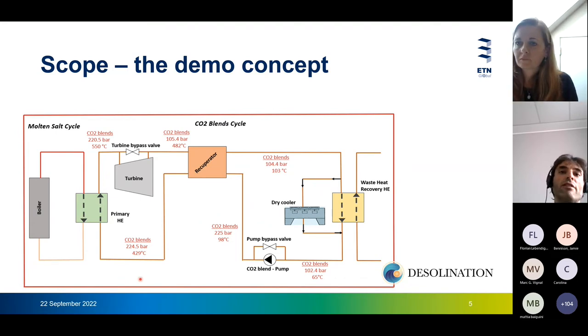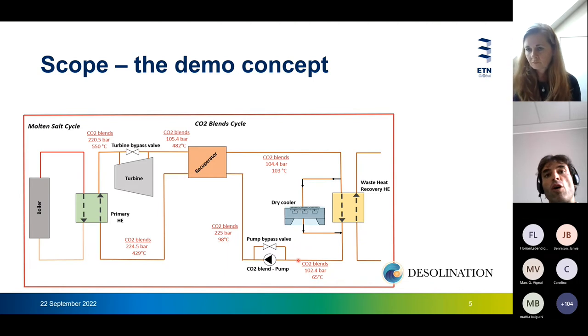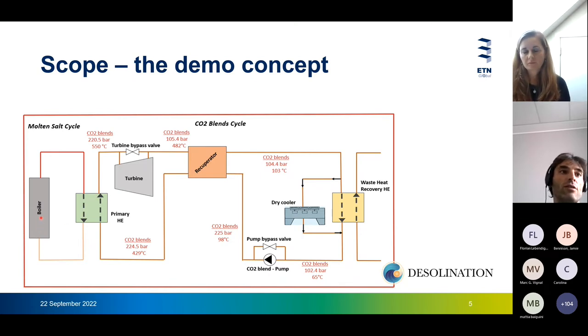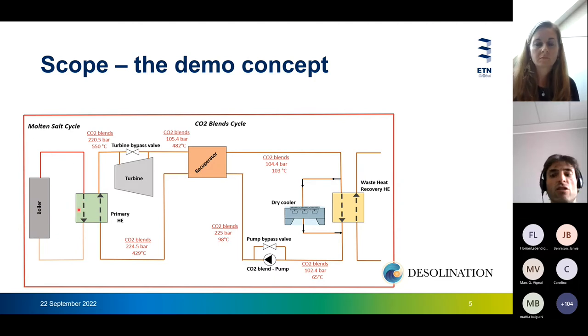This is what is going to be built in the upcoming years within the DESOLINATION project. It is a simple recuperative cycle where you have the pump, because the idea is that the CO2, thanks to the adoption of the blend, is in liquid phase at the inlet. It's compressed, it goes through a recuperator, a primary heat exchanger. We have a boiler to heat up the fluid, a molten salt boiler to be representative of a CSP application. Then we have a maximum temperature of 550 degrees C and a pressure around 220 bar. And finally, again it goes through the recuperator for being cooled down.